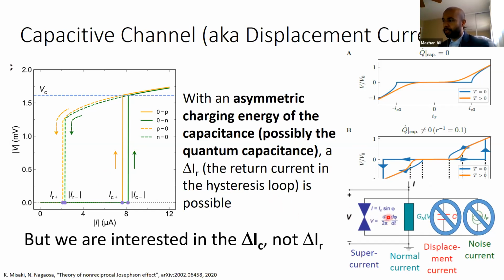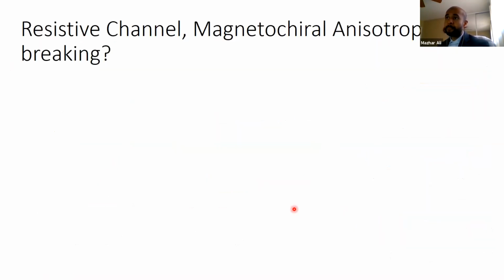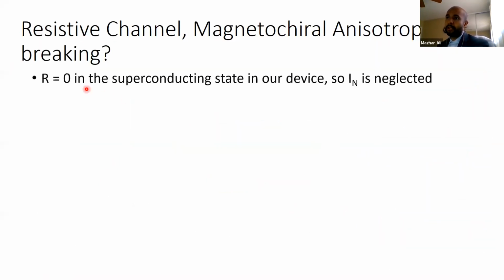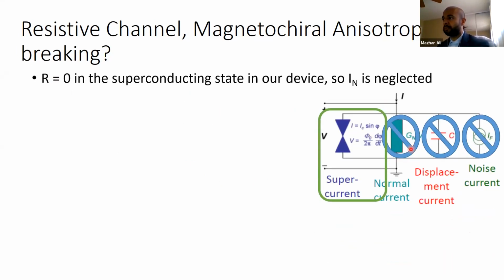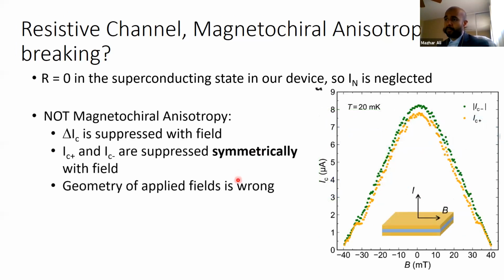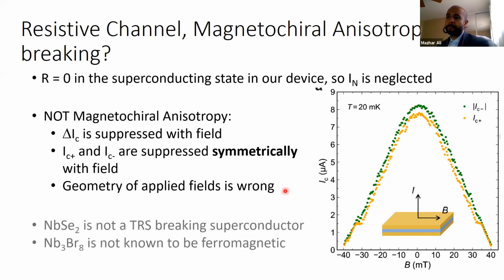So now we're left with supercurrent and the normal current contribution. Well, let's just really quickly tackle those. As I showed you guys earlier, we definitely do go to zero. We actually go to true zero resistance. So there is not a significant contribution from the normal current. It's all shunted through the supercurrent. So like we said already, it's not magnetochiral anisotropy for a variety of reasons. Even the geometry of what we've done is just wrong for even having a magnetochiral anisotropic effect. So that's not the driving factor.